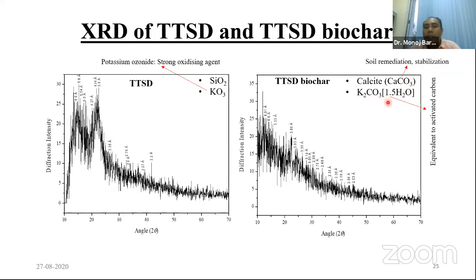Similarly, another element, that is K2CO3, can be identified from this kind of XRD spectra, which is basically equivalent to activated carbon. As we know, activated carbon again is very much helpful or useful for agricultural purposes. In most of the works, we see that activated carbons are artificially made in the biochar. But here, if we get this kind of elements on the biochar, it automatically has the equivalent property of the activated carbon. So this is how we can get some advantages if we do the proper characterization with the help of this XRD analysis.